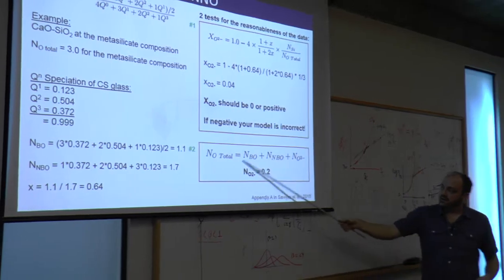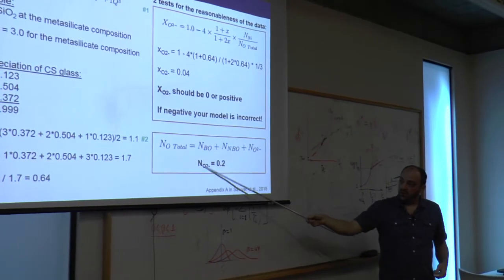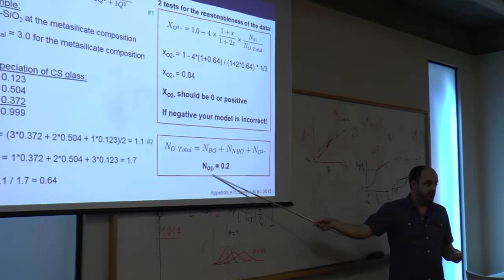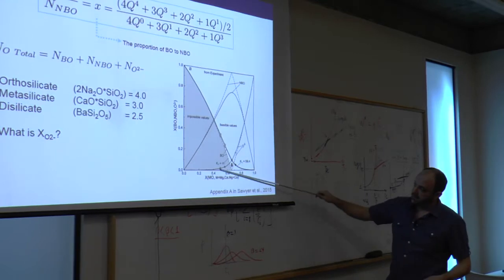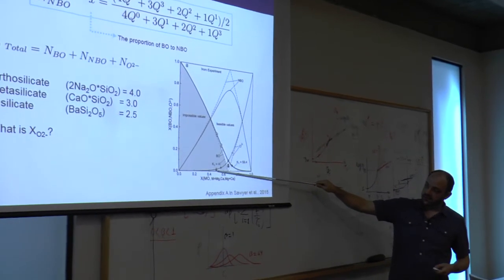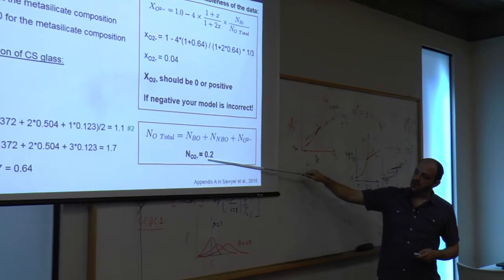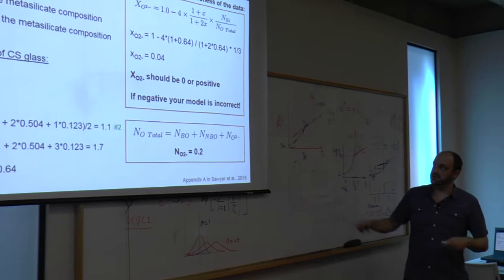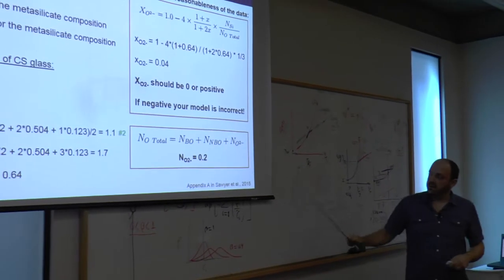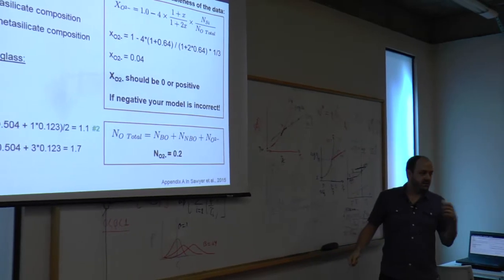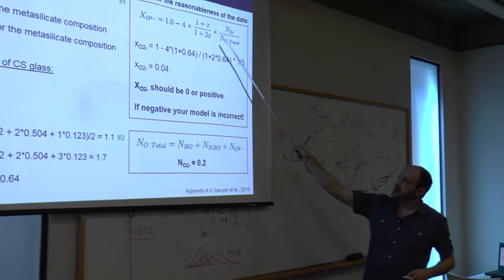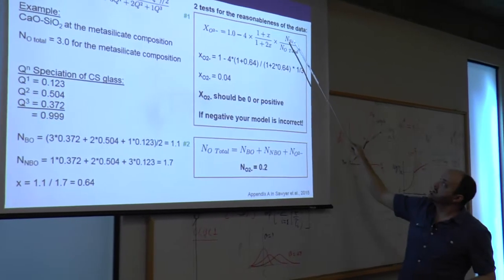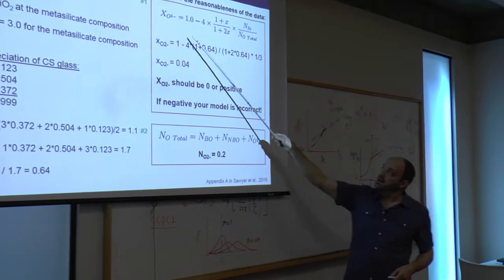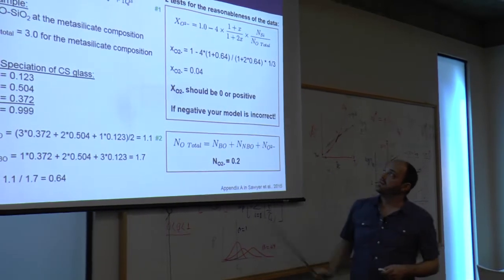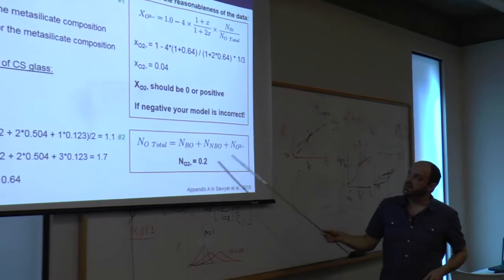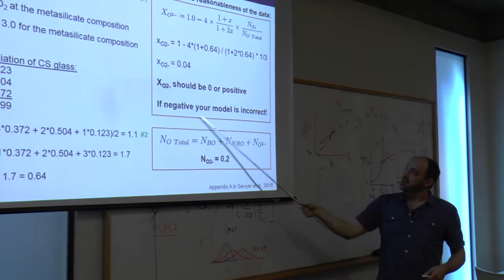So the first check is, do you get a reasonable value for the molar proportion of non-network oxygen? So going back, metasilicate is 50% modifier, 50% silica, and we said we have, in proportions, that's for the first part. Sorry. But whether you get a positive value or 0, if you get a negative, something is seriously wrong. The other relationship is this equation up here, which relates the total moles of silica to the oxygen, to the proportion of free oxygen. Again, I'll let you do the math. It's pretty straightforward there. But if you get a negative number, your model is incorrect.